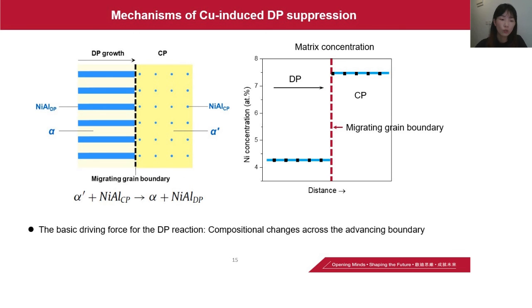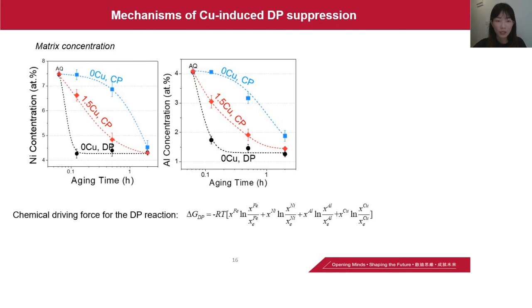We calculated the nickel concentrations in the matrix of the DP and CP regions across the migrating grain boundary. We found that the nickel concentration in the CP regions is apparently higher than that in the DP regions. Thus, we concluded that a concentration difference across the migrating grain boundary provides the chemical driving force for the DP reaction. Well, based on this theory, we calculated the solute concentrations in the CP and DP regions of